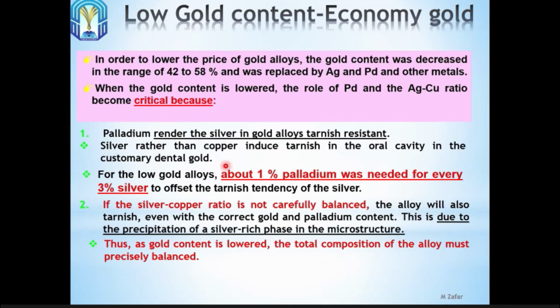And most important is the ratio of palladium and silver. For the amount of silver we add, 1% palladium should be added for every 3% silver. For example, if we add 3% silver, we will add 1% palladium. If we add 6% silver, we add 2%, to keep it balanced and not affect the properties. So therefore, if we are replacing gold, the proportion should be balanced carefully.